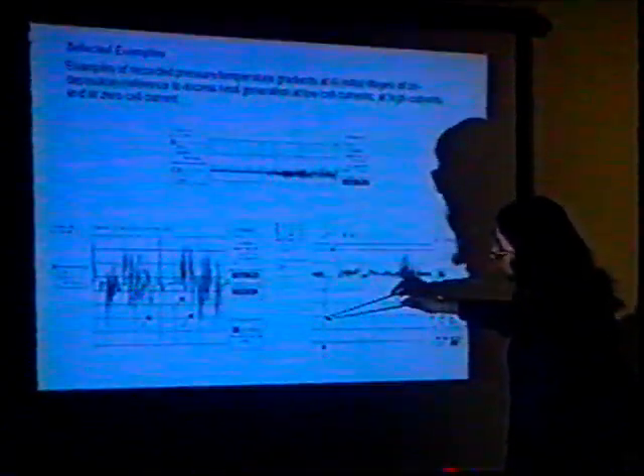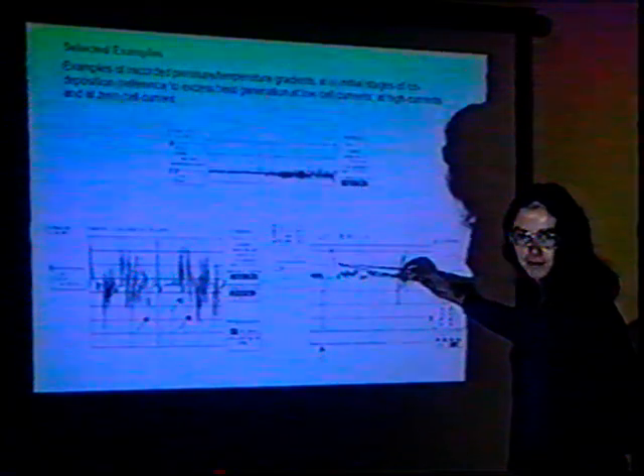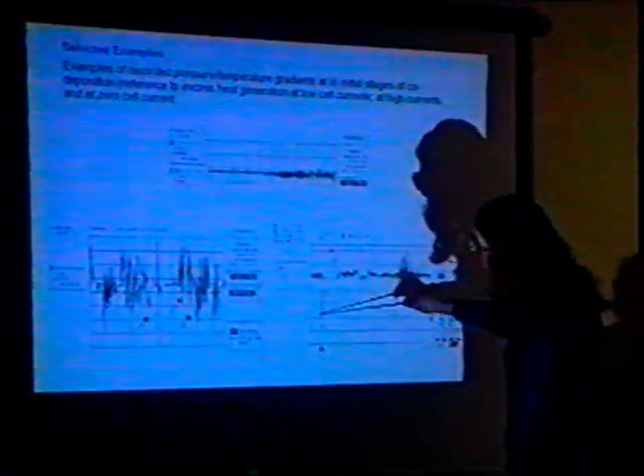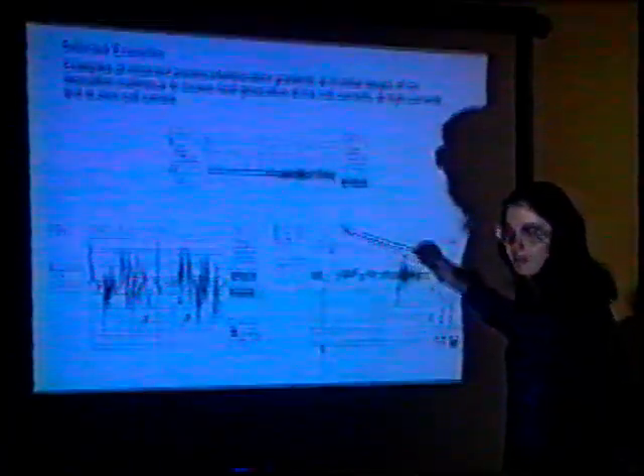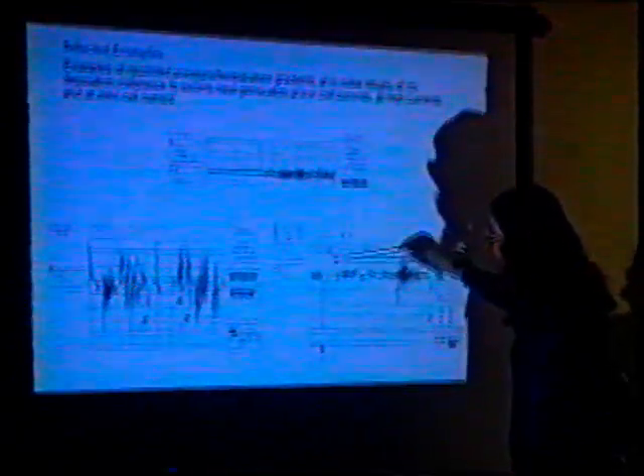If we look closely at this example here we see a pressure gradient, which has caused constriction of the crystal. And as I said before, when the crystal relaxes back, the area of these two peaks should be the same. And you can clearly see that the area of this peak is greater than this one. So there's another source contributing to that peak area. And if you think about it, if you have a heat source causing a pressure gradient, you're also going to have a temperature increase. And that temperature increase is going to cause the crystal to expand. And so we have both of these features contributing to this area.